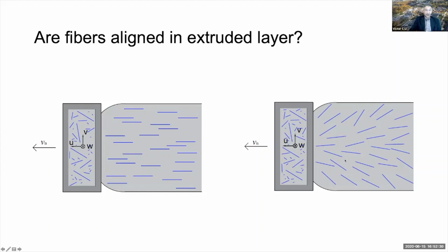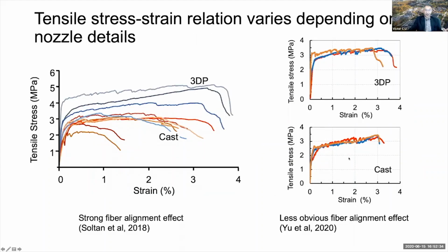It turns out that both concepts have been supported depending on the details of the 3D printing process. For example, on the left, tensile stress strain curves clearly show that the 3D printed specimens have higher strength as well as higher ductility compared to the cast specimens made of the same material but processed by casting rather than by 3D printing. Now this 3D printing is actually a simulated 3D printing with a caulking gun.